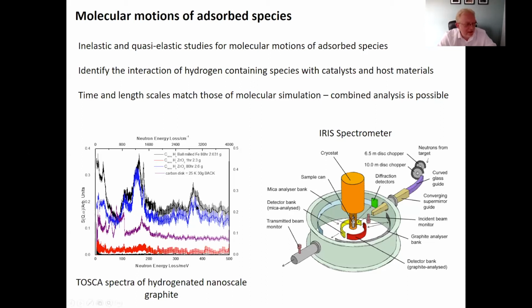And you can then look at the evolution of these hydrogen forming reactions. And why is that important? Well, this is very important for things like catalysts. If you think about the water gas shift reaction, where you're making carbon monoxide and hydrogen, you get a lot of carbon deposition on your catalyst. And if that deposition is graphitic, then that catalyst becomes deactivated very rapidly, whereas if it's aliphatic, you can actually burn it off and hydrogenate it off and regenerate your catalyst. So we're actually looking at catalytic materials by spectroscopy. It gives you a very deep understanding of the processes and the mechanisms of those catalysts, for example.